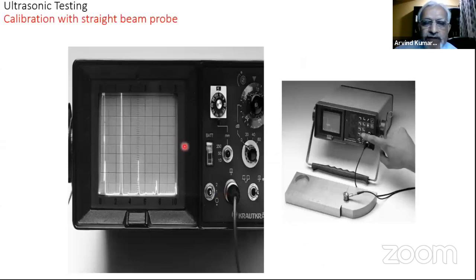Now, how to do the calibration using a single crystal probe, this is not a TR probe. This block that you see here is called a V1 block. It's a standard block having standard dimensions. This thickness is 25 mm and this is 100 mm. We are talking about only 25 mm. So if I keep a probe here, the straight beam goes 25 mm and comes back, and on the screen I'm seeing how many peaks?